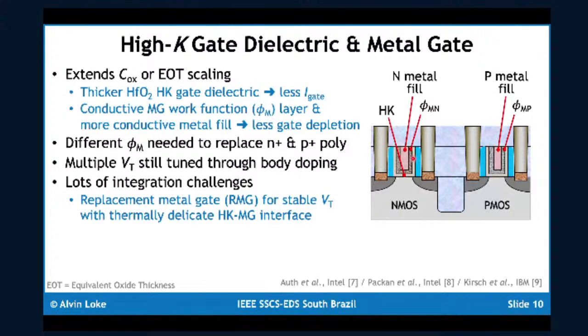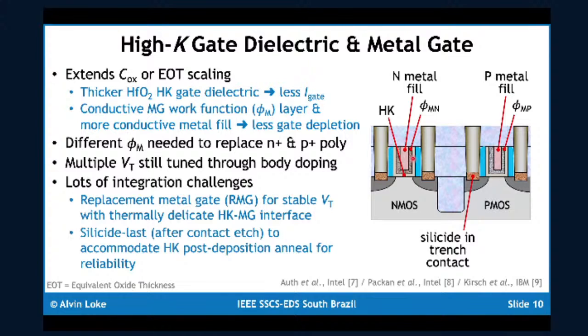Another integration challenge associated with HighK metal gate is the resequencing of the silicide module. One requirement of a HighK dielectric is that it undergoes a post-deposition anneal for gate oxide reliability. In order to do that, it inadvertently destroys the low resistivity of the silicide you use. So you have to postpone the silicide module until after the HighK deposition step.